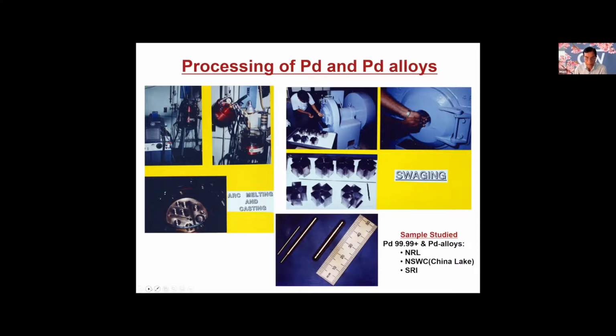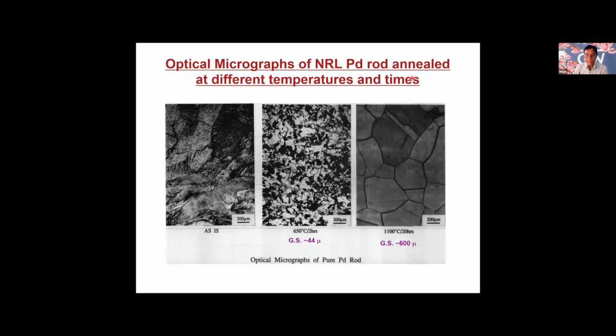So moving forward, this is a palladium rod only. I just wanted to give you an idea how the grains or the structure changes. Here, this is the material as received. And this one is material annealed at 650 degrees centigrade for 2 hours. You can see the grain size. The grain size here is around 44 micrometer. When you anneal it at higher temperature, the grain size increases. And here it is roughly 600 micrometer. Again, this material will be harder compared to this one here. And I mentioned before that grain size effect will be there on the material.